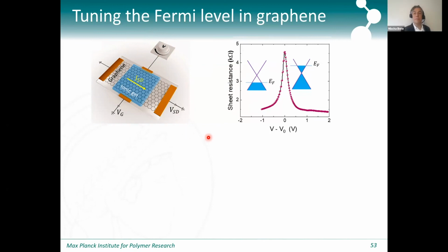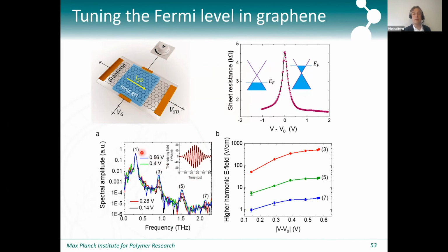And then, maybe not too surprising, you see indeed that if you apply a higher gate voltage, so you dope the graphene more, you get more efficient high harmonics generation. It's a little bit small, but the dark blue here is the largest gate voltage, 560 millivolts. Here you see the efficiency of the third, the fifth, and the seventh harmonic as a function of gate voltage. And you can see that indeed we can go up, say, an order of magnitude in the third harmonic by more efficiently doping the graphene.